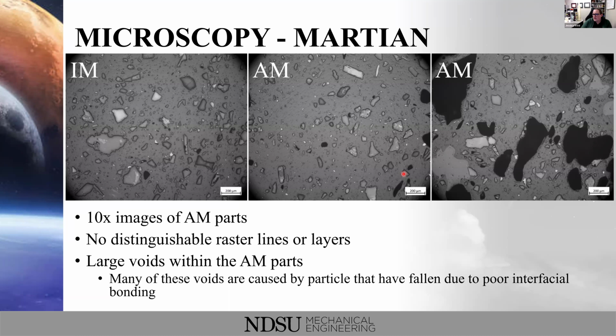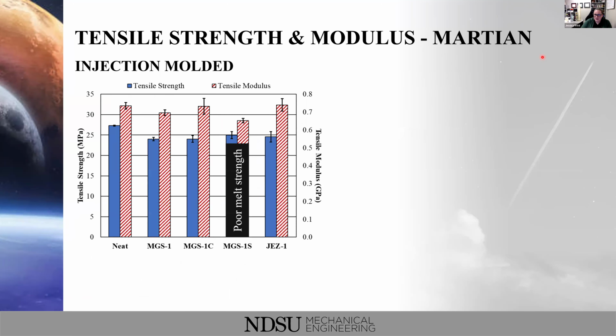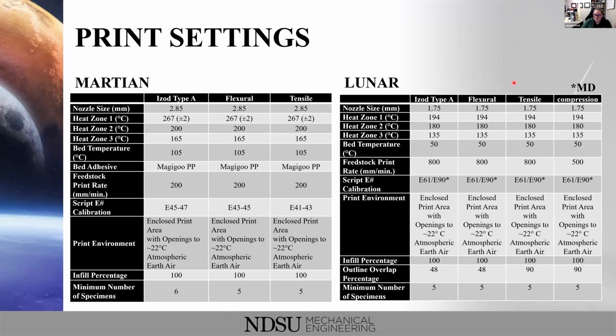How did you control for bed adhesion and warping or shrinkage during printing? That's a great question, Charlotte. So for our PLA, we just heated the bed. The bed temperature is 50 degrees centigrade for our PLA, and it did beautifully. We had no issues with adhesion at all with those parts. And then for our polypropylene on the Martian side, we had a 105 degrees C print bed, and then we used the Magigoo PP. So it's basically a glue stick to adhere it. And that worked absolutely wonderfully to get the polypropylene to adhere to the bed.